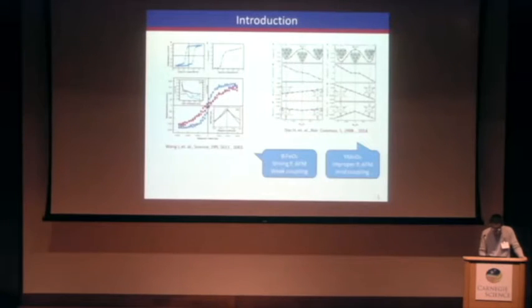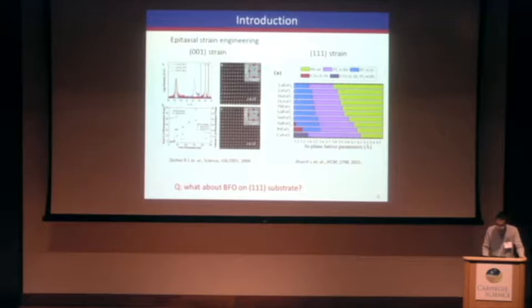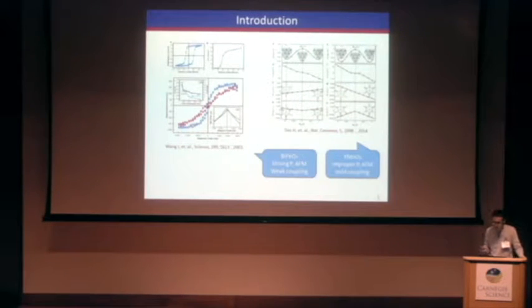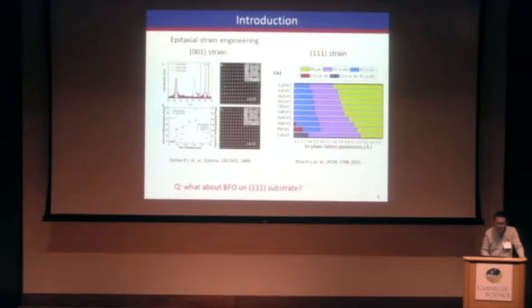We are talking about this because we want to deliver the message that multiferroics are quite rare, and one useful method is epitaxial strain engineering to create new multiferroic phases. For example, when using strong compressive epitaxial strain, the T phase can be generated, and the spin-orbit magnetoelectric coupling can be very strong here. Also for rare earth manganites and rare earth ferrites in the hexagonal phase, the large tensile epitaxial strain can also generate the yttrium manganite type hexagonal structure.